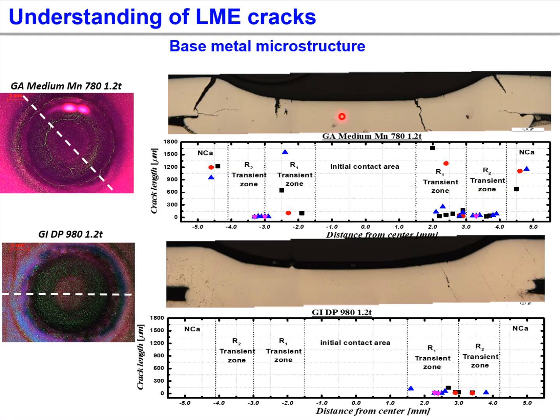Our research group also found that there is a large difference in LME crack sensitivity between medium manganese steel and DP steels, even with extended welding time. In the case of medium manganese steel, a large shoulder crack has been observed with extended welding time. In the case of DP steels, no large shoulder crack was found even in the extended welding time condition.